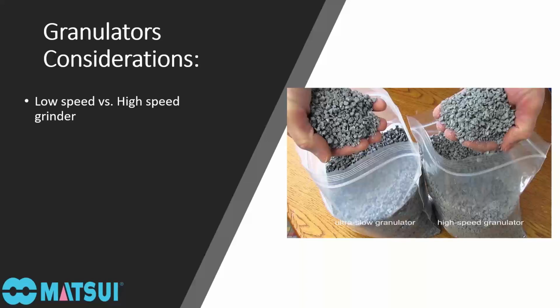Ideally, the runners and sprues are fed by a sprue picking robot or a regular traversing robot or even a conveyor. So each cycle, a sprue or runner would be dropped into the low-speed grinder. It would grind that material up. And we're grinding the material right next to the injection machine, so that material can be reused right away. Sometimes it doesn't have to be re-dried. You can take that material and send it back with the virgin material to the drying hopper, or if it's being used fast enough, the regrind material will not have to be re-dried, and you can just blend it with the virgin material, go into the injection machine feed throat.